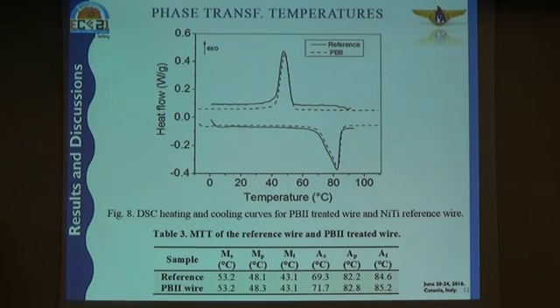And what about the phase transformation? Now we have two wires, one treated and another reference. So we see the difference of what happened when we treat the wire. What about the temperature of phase transformation? Here's the solid wire, the reference wire, and the dashed line is the treated wire. As we can see in the graph, there is no significant change in the temperatures, as we can see in this table below.